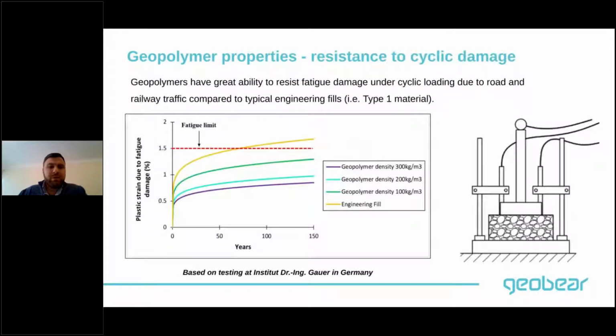Okay. Also, furthermore, geopolymers also have great ability to resist fatigue damage under cyclic loading. So if you take a sample of a geopolymer and you start applying cyclic loading, which is what you normally get under railway loading, the geopolymers would have a very high fatigue life. So it will take quite a while for it to actually start creeping and cracking.